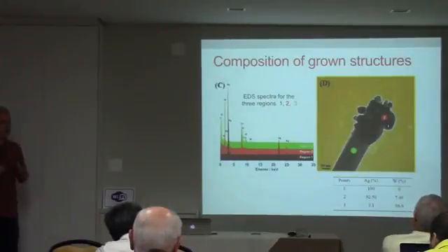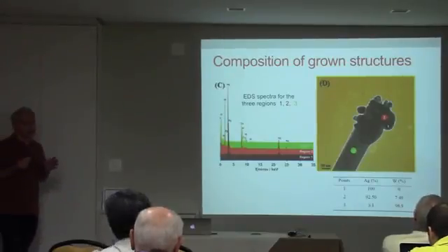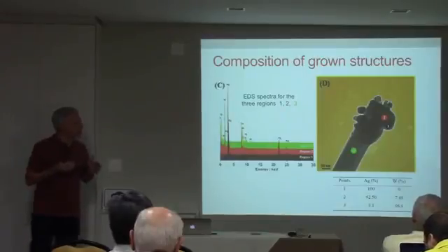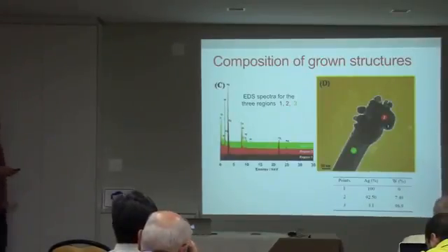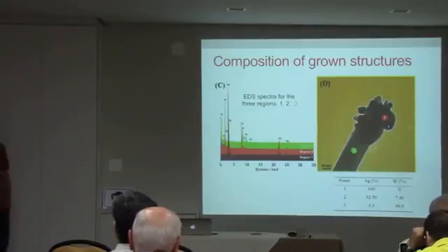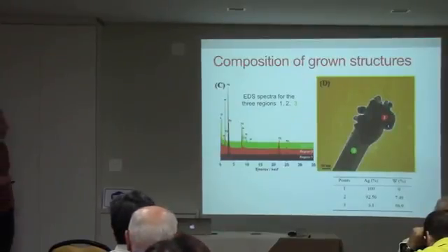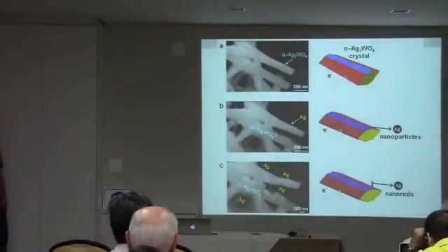So when we just observe, we are injecting electrons. We are irradiating electrons on the sample, and then this originates a process in which silver, metallic silver, is grown. This is a very novel system.